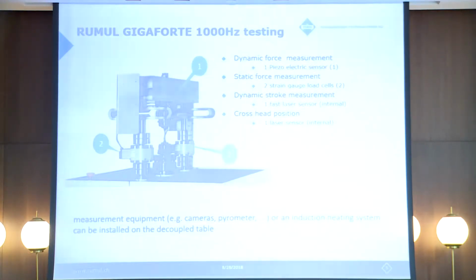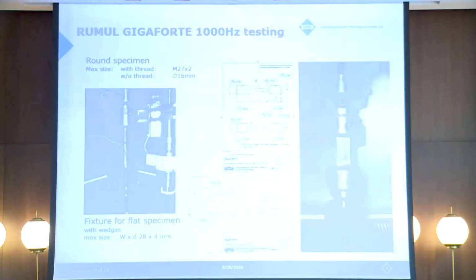And also for the dynamic and static displacement measurement, we have 2 separate systems based on laser technology. The table around the machine is not connected with the vibrating part, so we can place here some equipment, a camera for example, or maybe a heating system. There is the possibility to use normal specimens known in fatigue testing, round specimens with a thread for the high load, but there is also the possibility to test flat specimens with a fixture that is working with wedges, or also a fixture for round specimens without the thread. And one can even test small components as long as they are stiff and small.